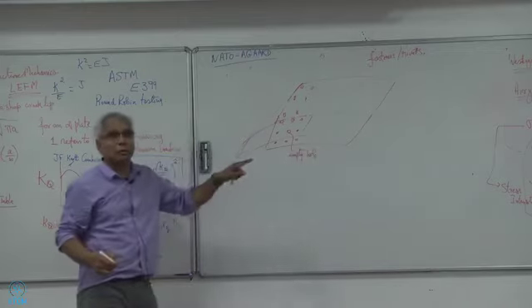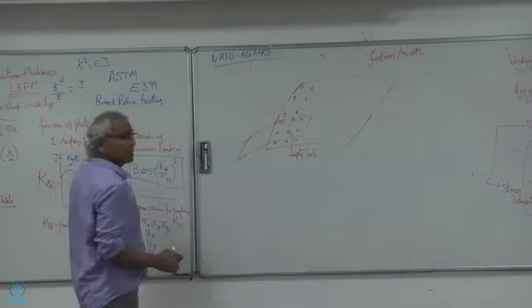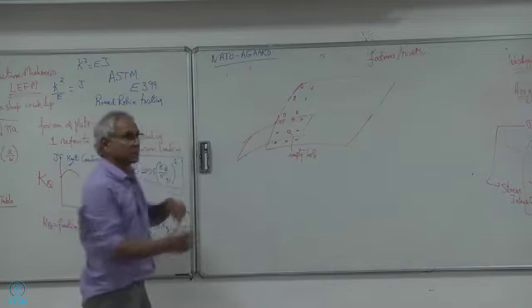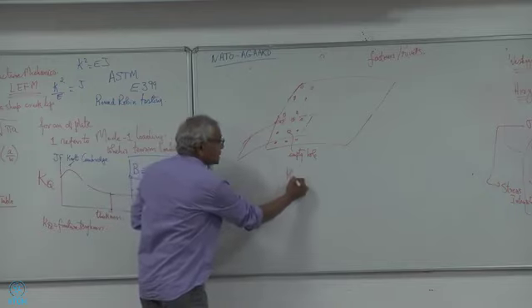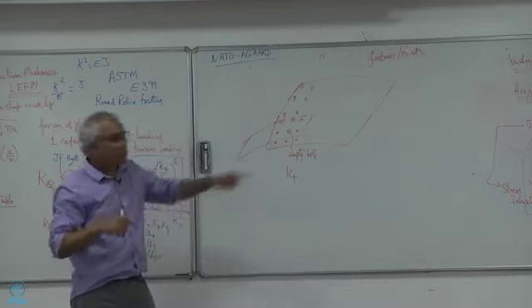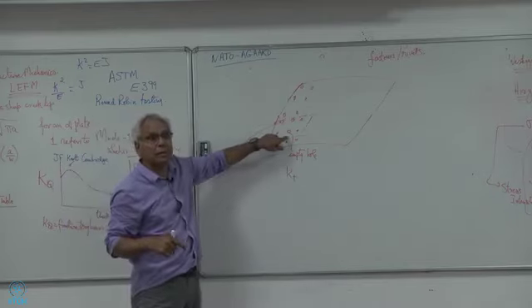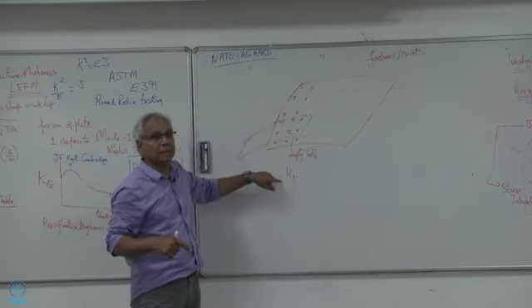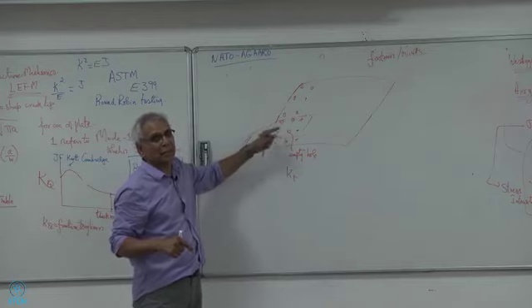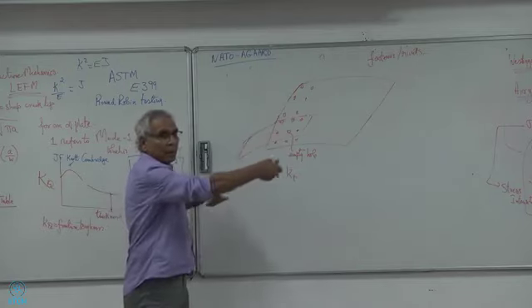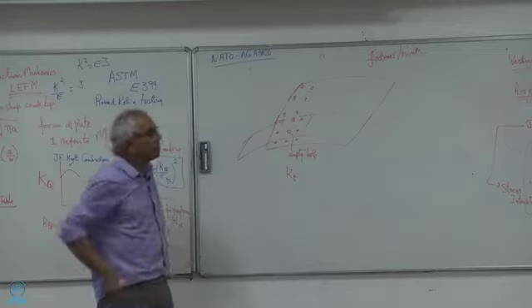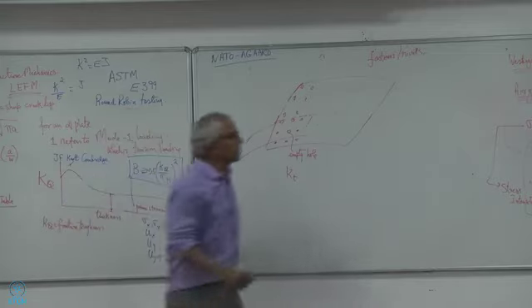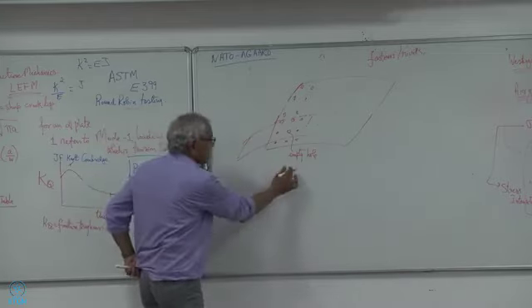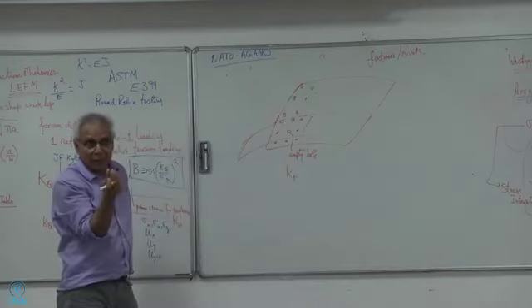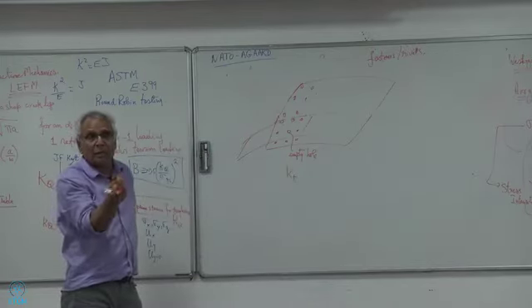At that time, you have to apply not this analysis, but the stress concentration factor, K sub T. K sub T. So if your fastener falls off here, okay, so you're applying K sub T. Of course, things are not that simple in life. It's not a uniaxial loading anymore. It's probably going back and forth this way. Shear loads, maybe. So just like we did K1, well, okay, let me stay with this for a second. So then you have to use the K sub T because you have an empty hole, where the stresses are going up.